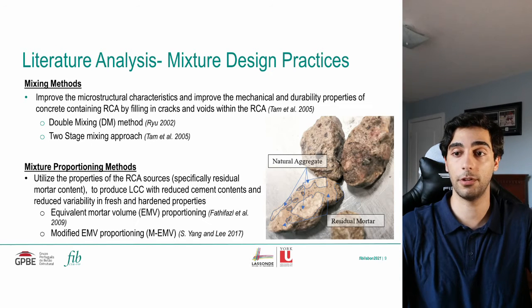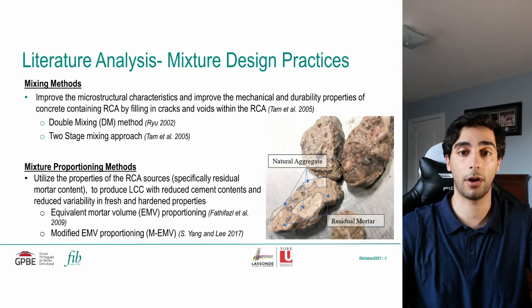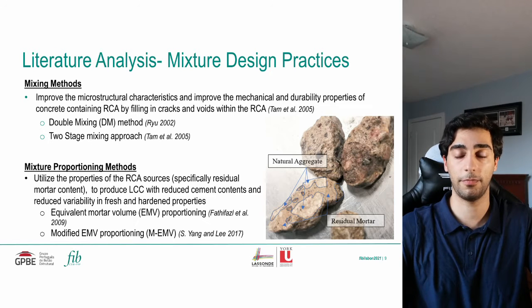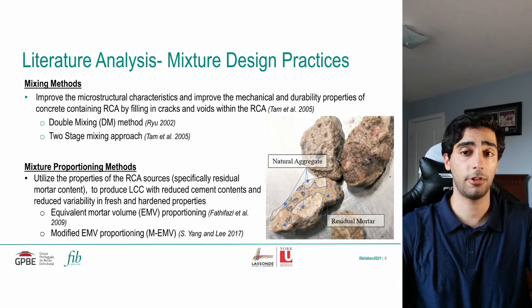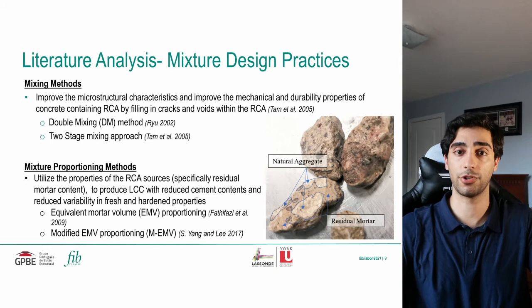Mixing methods, which have been utilized to improve the microstructure characteristics, as well as the durability and mechanical strength properties of mixtures incorporating RCA, and then mixture proportioning methods, which have utilized the properties of RCA sources effectively within the mix design to improve the fresh and hardened properties of the low-carbon concrete mixtures. Now, within each of these, we focus on two different methods. Within the mixing methods, we focus on double mixing and two-stage mixing, while in the mixture proportioning, we focus on equivalent mortar volume and modified equivalent mortar volume proportioning.